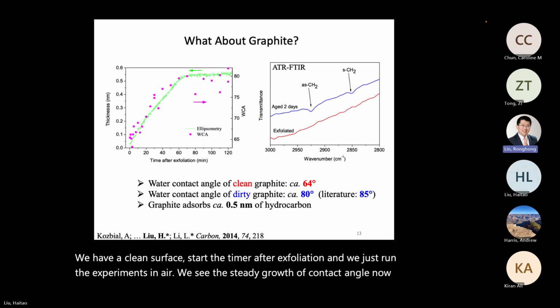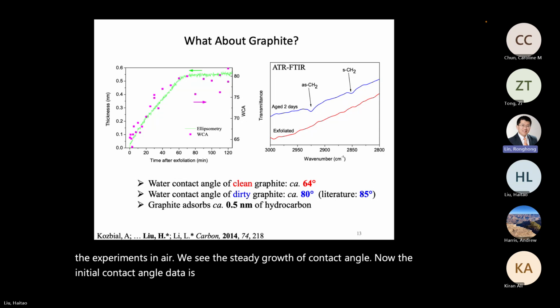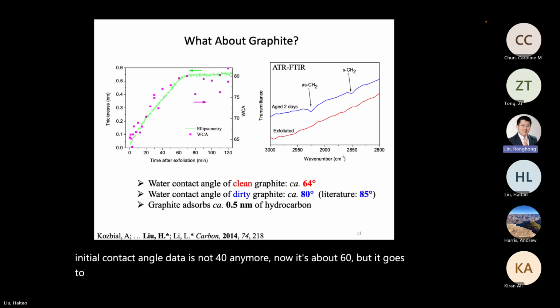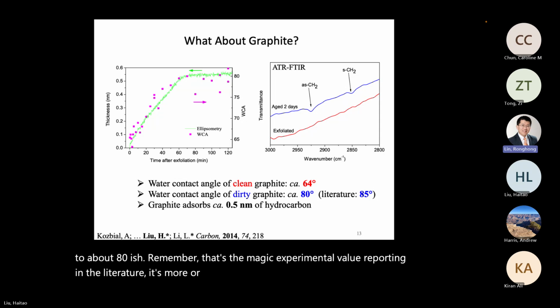Now, the initial contact angle data is not 40 anymore. Now it's about 60. It goes to about 80-ish. Remember, that's the magic experimental value reported in the literature. It's more or less linear and then plateaus.